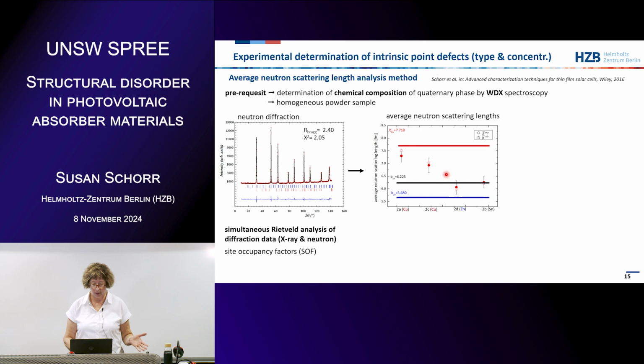And you see already that the value for the 2A site, where normally copper is, is definitely below the copper line. And also the value for the 2C site is even more below the copper line. So these 2 points should be on the copper line because these are the copper sites. And this already shows you that you have not only copper on this position. Also the value for the zinc position, this one, should be on the blue line and it's lifted up.